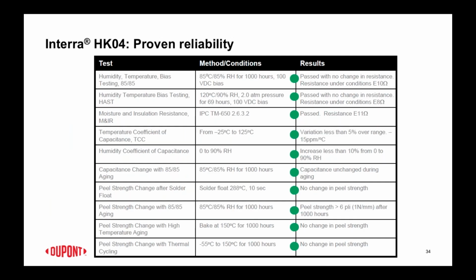And this is just, I'm not going to go over all the details in here, but you can see we've gone through all the different temperature, humidity, bias testing, moisture, insulation resistance. We've actually even done CAF testing. It sounds interesting, say, why would you do CAF testing since there's no fibers here to cause the problem? Well, people still want to be comfortable that there isn't a CAF-like failure that can occur. So we've done over 1,000-hour testing, 100-volt bias, and we've been able to successfully pass the CAF testing as well as all these other traditional reliability testing.